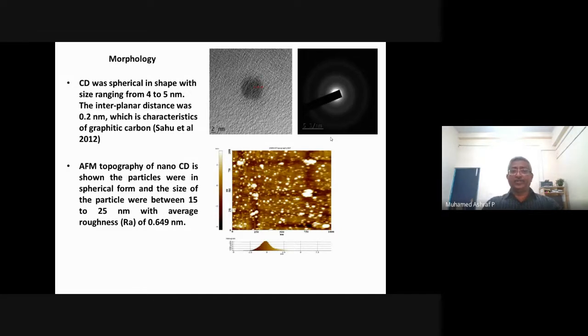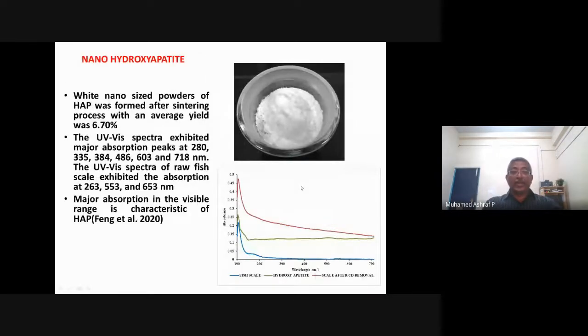And then what is the morphology of that? You can see purely that it is a TEM image. This is an image of 4 to 5 nanometer size particles, and in the spectrograph, if an inorganic material were present in the system, you would get a lot of dots over it. Here you can see only the electron cloud of the carbon dots, which implies that it is a purely organic nanomaterial that can be used for different purposes instead of inorganics. And this is the AFM topography of the material.